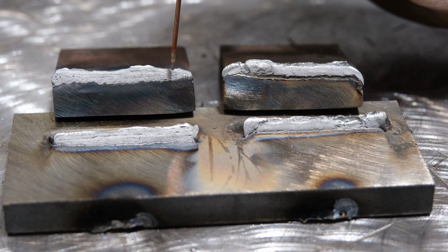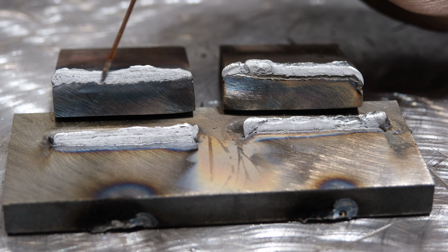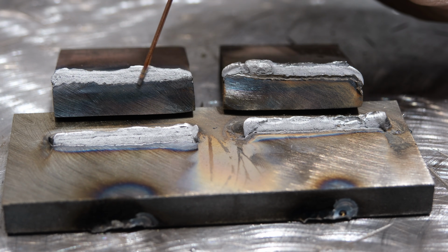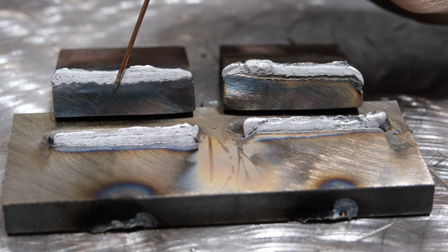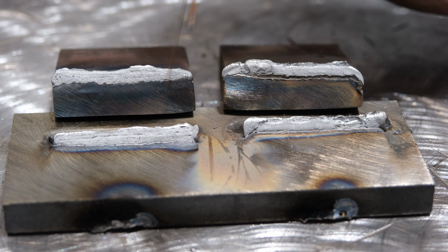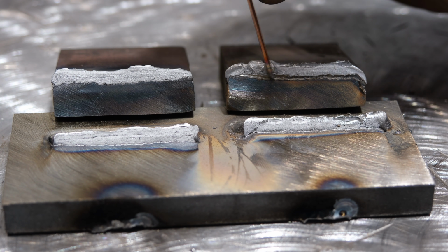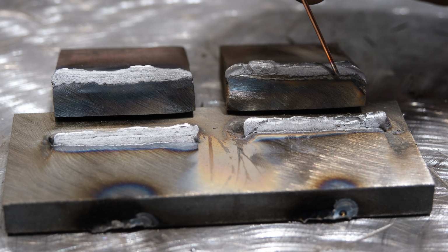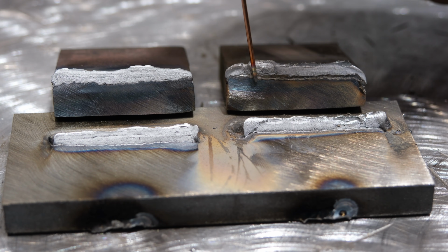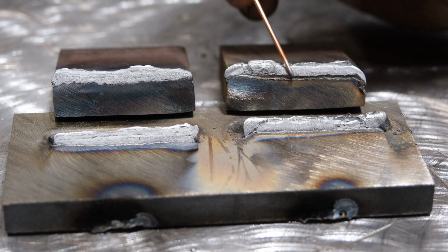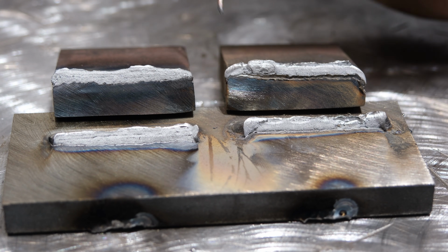Now, the TIG weld, without a doubt, has more penetration. It broke down that edge completely and fused in there. In comparison, like I said, this line here is not a line of fusion. It's just where the flux more or less was sitting. So there is far less root penetration on this than with the TIG weld.